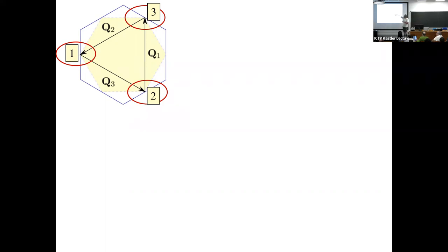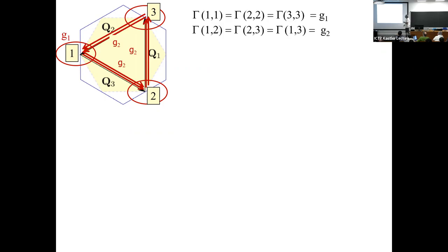Because of symmetry, there are three non-equivalent points where you have Van Hove singularities in the density of states. The other three are related by K to minus K symmetry. And the number of interactions is two because of the symmetry. So you still have the same point. They have one interaction inside the patch, another interaction between the patches, but the interaction between patch one and three is the same as between one and two and between two and three by symmetry. So we have a 3x3 problem because there are three different corners and two interactions.